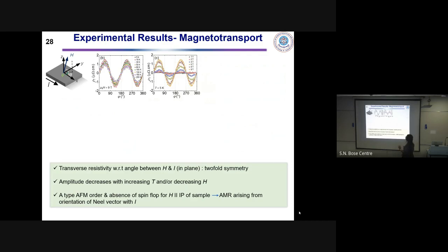These two here show the transverse resistivity with respect to angle phi. Now, what is phi? Phi is the angle between the applied magnetic field H and the current I, where I is in the plane of the sample and H is also in the plane of the sample. In this configuration, we have seen a harmonic behavior of rho t versus phi, and its amplitude decreases with increasing temperature and with decreasing magnetic field.